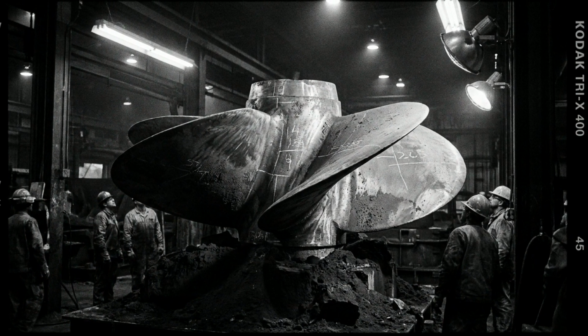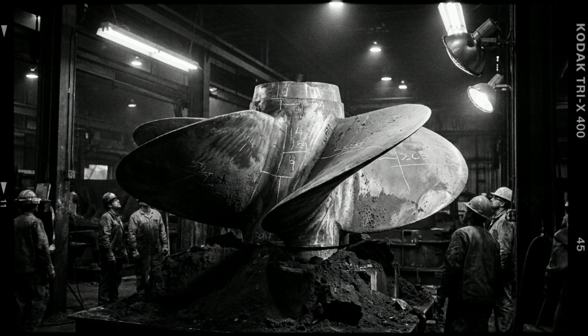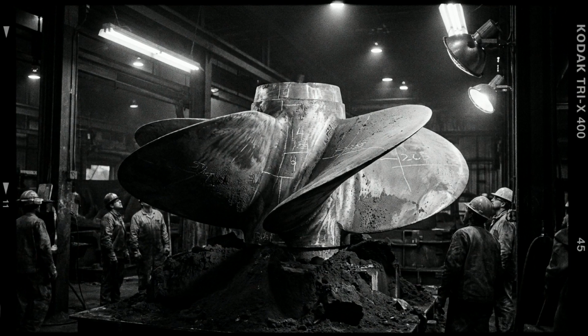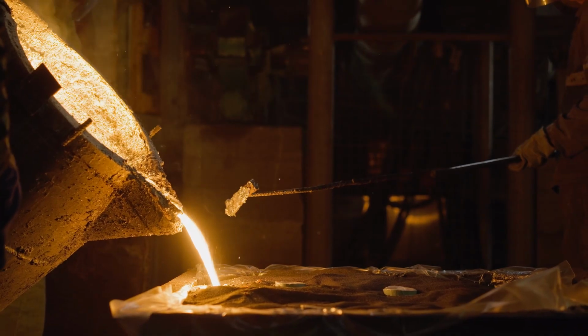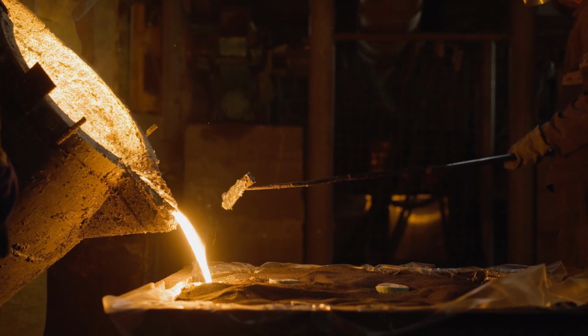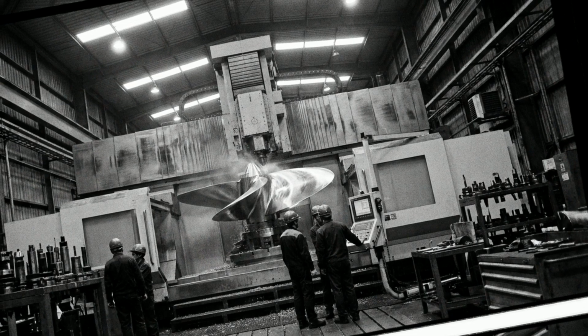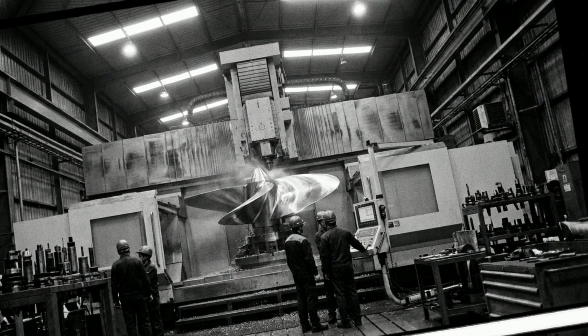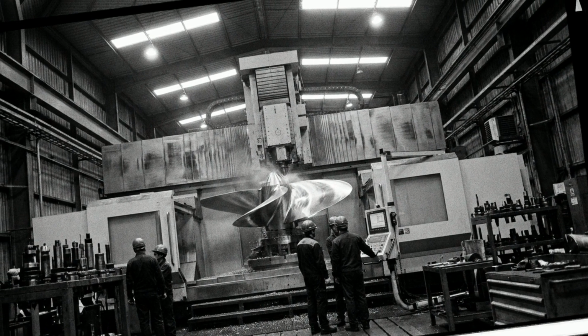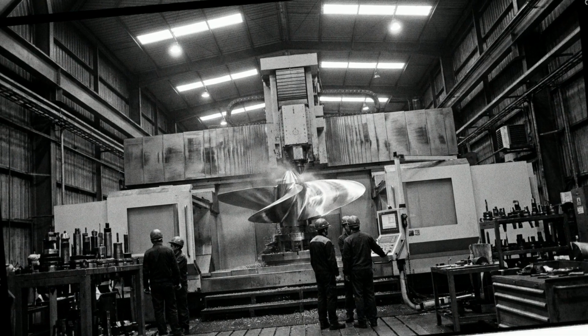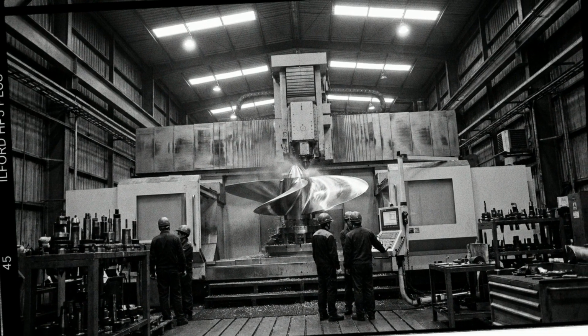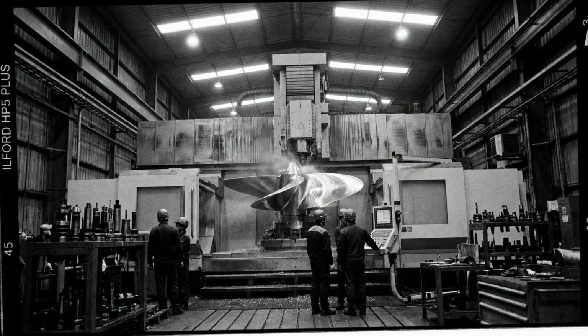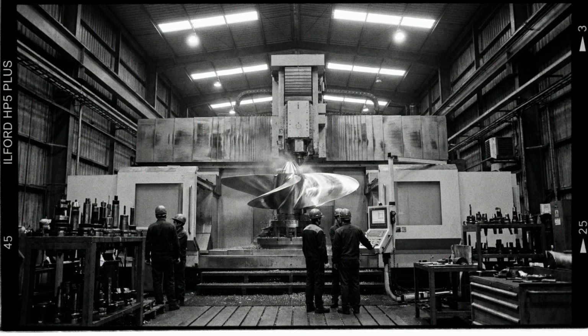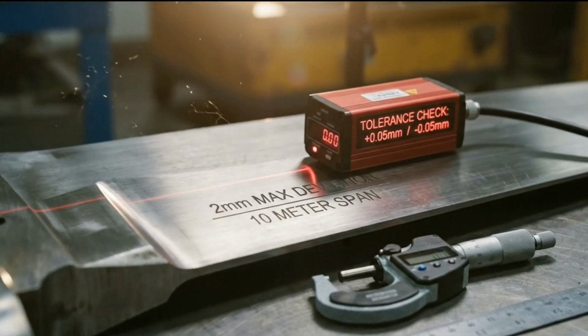After casting, the propeller spends weeks in controlled cooling. Rushing the cooling of a 100-ton bronze casting risks thermal stresses that crack the component from the inside. The foundry knows this. The cooling is planned as carefully as the pour, and then the machining begins. The blade surfaces are machined on purpose-built 5-axis milling machines with working envelopes large enough to accommodate a 10-meter propeller.